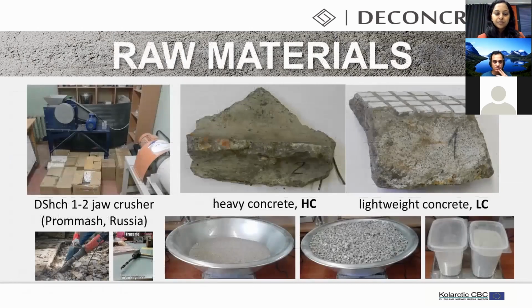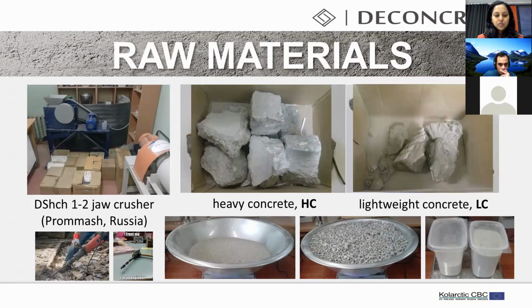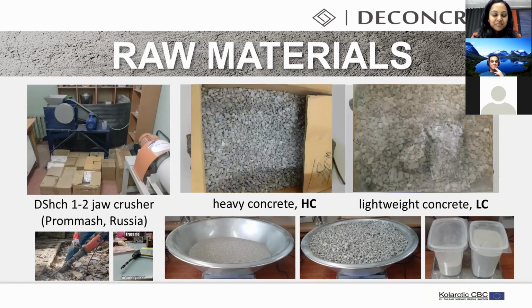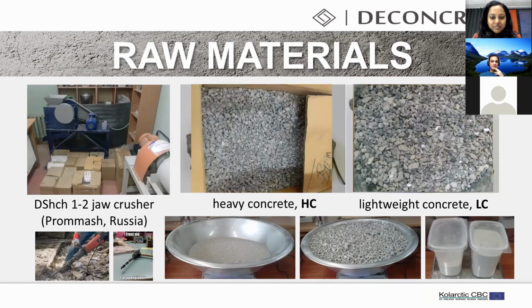So we took the samples and manually crushed them to pieces of maximum 120 millimeters in size. Then these concrete fragments were crushed using a jaw crusher with a hard-to-pronounce name, DShch 1-2. It's a Russian jaw crusher. Don't try to pronounce this name at home; it's only for Russians. So we used this jaw crusher and obtained those screens that you can see, of heavy concrete and lightweight concrete. Lightweight concrete also contains a lot of ceramic mosaic and a lot of shungizit, the mineral insulation.